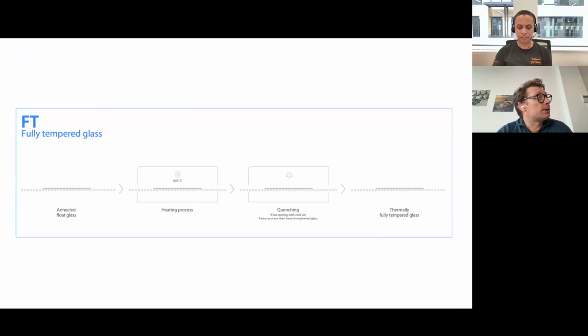To add strength to the glass: what is produced in the float line is a glass which is called annealed, and that means that we're trying to take all the stress out of it, although it can have a small amount of stress, sort of 2 to 3 megapascals. But tempering is the process by which the glass is heated up just past the glass transition temperature, and it's cooled down quickly in the quenching furnace with air. And this locks in stress into that panel, and I'll talk a bit more about that later. And this affords a glass with greater strength. So the surface is typically around 120 or 160 megapascals, so a much stronger piece of glass, but it does have its drawbacks.